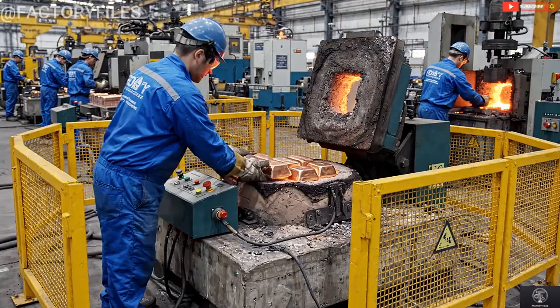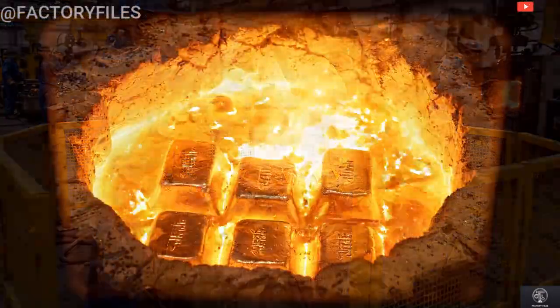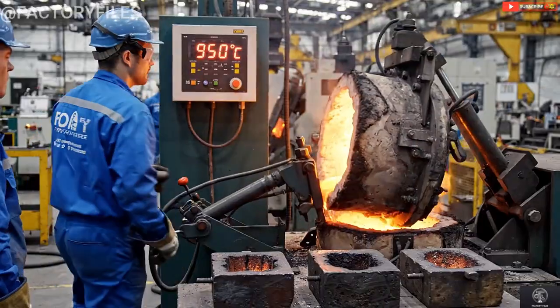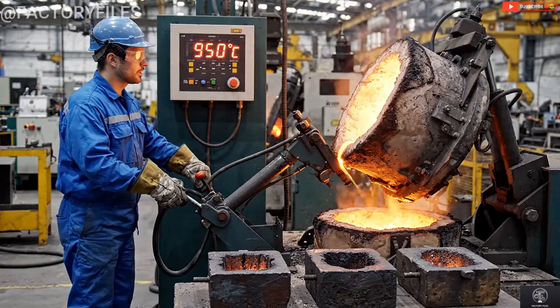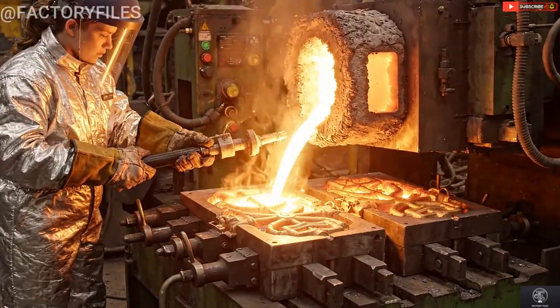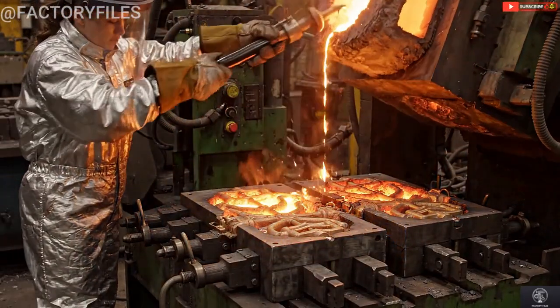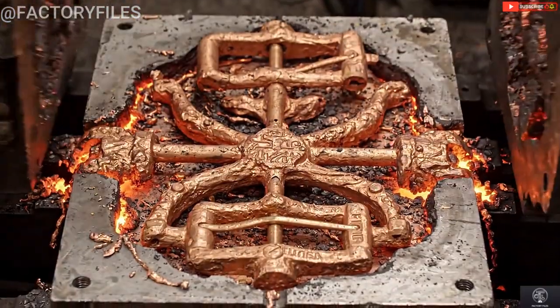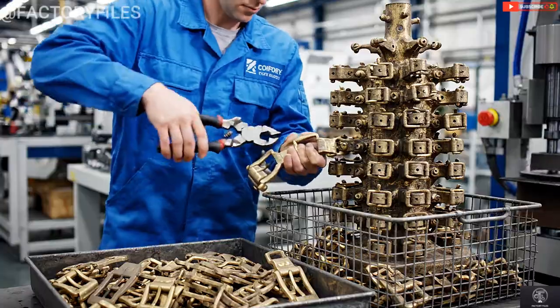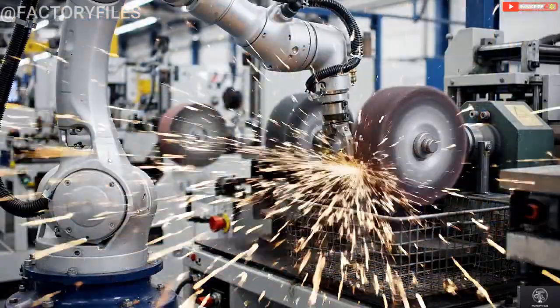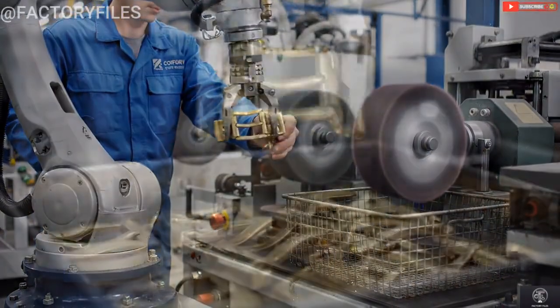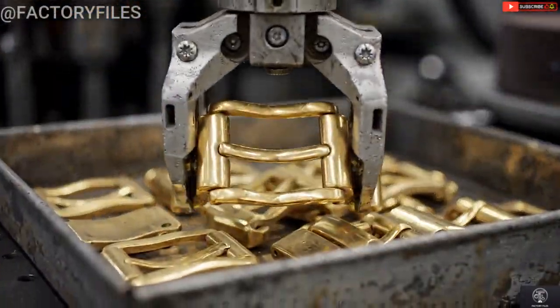In the hardware foundry, a high-frequency induction furnace melts copper and zinc alloy ingots at over 900 degrees Celsius. The molten metal is poured into precision steel molds where it fills every detail of the buckle cavity, and after cooling, the mold is opened. Pneumatic pliers separate the raw buckles from the casting tree. Then a 6-axis robotic arm moves each buckle through polishing.